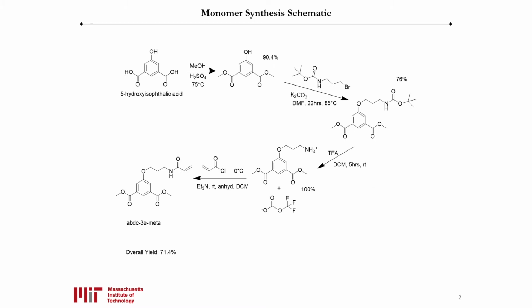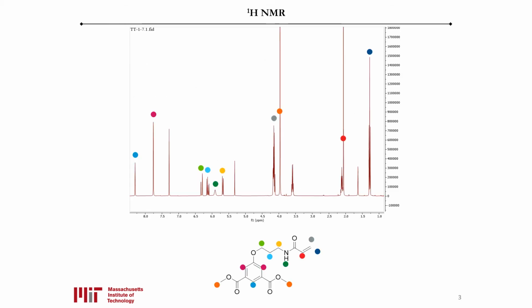The monomer was synthesized from starting material 5-hydroxy isophthalic acid, which underwent a Fischer esterification, an SN2 reaction, a Boc deprotection, and a nucleophilic acyl substitution. To characterize the monomer, a hydrogen NMR was taken, which then verified the synthesis of our monomer.